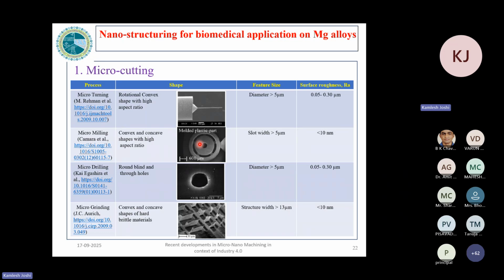Here are some of the features which we can see. In micro cutting, we can produce rotational convex shapes with high aspect ratio. This is a needle, and you can see the diameter of the needle is in the range of 5 micrometer, and the surface roughness which can be achieved is in the range of 0.05 to 0.3 micrometer. Similarly, there is a plastic molded part where we can see a slit, which is also in this range, and the surface finish is in the nanometer range. This is from micro milling. The references are given. Holes can be drilled using the micro drilling process. The size of the hole is again in the range of 5 micrometer, and we can make convex and concave shapes in hard brittle material. You can see the structure width is in the range of 13 micrometer, and the surface roughness is in the 10 nanometer range.